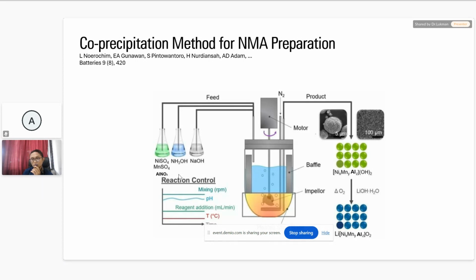We have to control the pH, yeah. The pH should be around 11.5, or maybe more than 11 but below 11.5. So this is a very sensitive factor that we have to consider to do this experiment. So we have to control this pH very carefully, yeah.